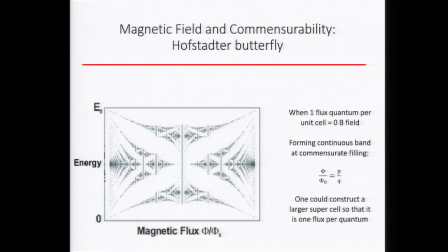Those correspond to these straight lines. That's when your system starts to form some supercell, some mini subbands. For example, in this 1/2 ratio, you can reconstruct your unit cell into 2 unit cells per node. So the new unit cell is twice the size of the original unit cell. And in this case, the new unit cell has 1 flux quantum. Then it's as if there's no magnetic field applied, so you reduce to a problem without magnetic field. People have seen this effect.